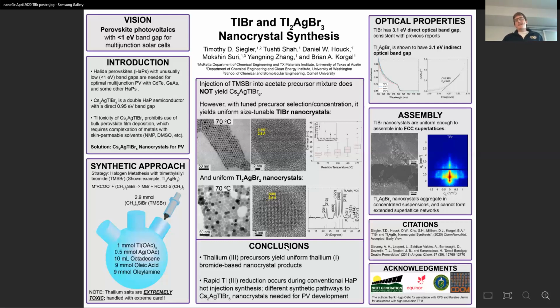This result that we've achieved, though, does provide some insight into synthesis of cesium silver thallium bromide. We have observed that our thallium-3 precursors yield very nice nanocrystal dispersions, very nice nanocrystal products, but they all incorporate monovalent thallium. And in fact, there is nothing that we can really do outside of changing our ligand composition that will prevent the reduction of this thallium-3+ on a very rapid timescale.